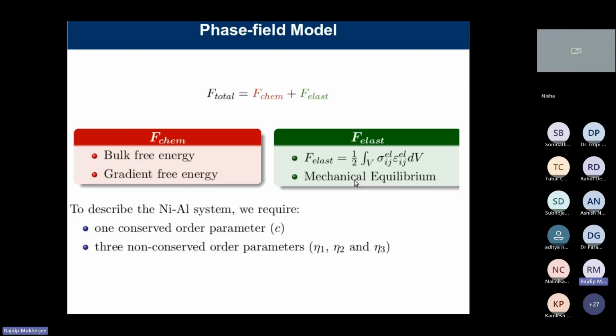So that is why we solve a mechanical equilibrium equation to get the displacement field. From there, we can get the strain field. From there, we can get the stress field, and we can calculate the elastic energy of the system and incorporate it in the total elastic energy of the system. The bulk free energy part we can get from Thermo-Calc or the CALPHAD approach. The gradient free energy, the interfacial energy, we can get either from literature or from atomistic simulation. The elastic part we need to calculate if we know the elastic constants from atomistic simulation and the misfit strain. Then by solving the mechanical equilibrium equation, we can get the elastic energy.